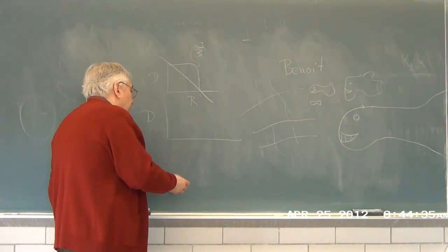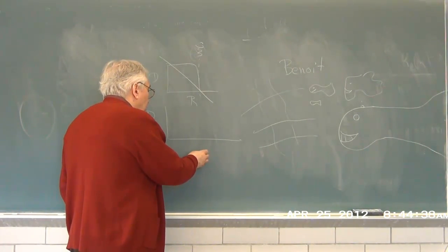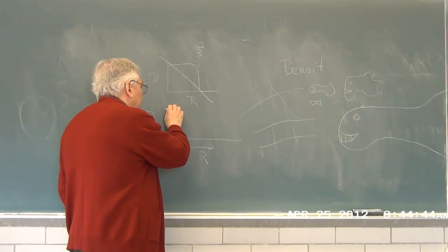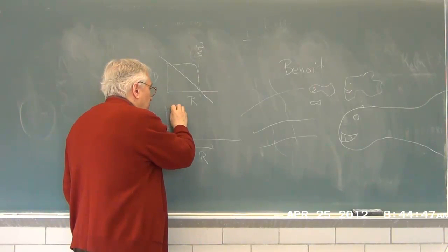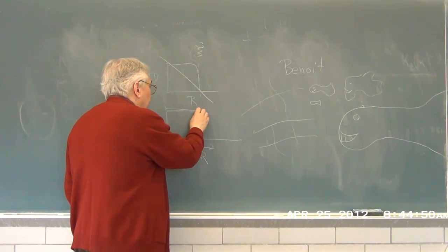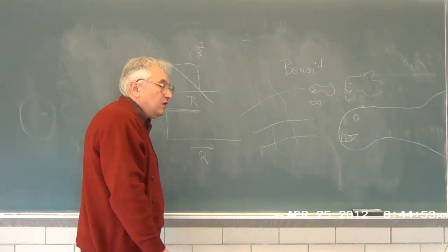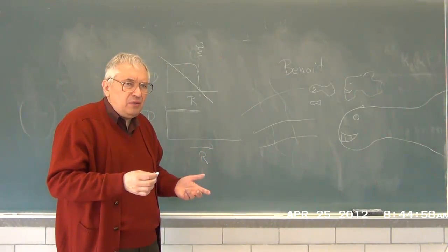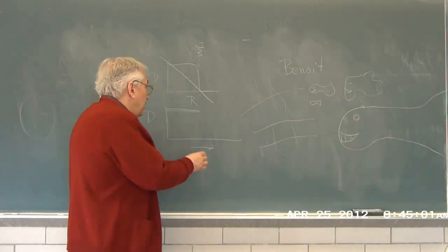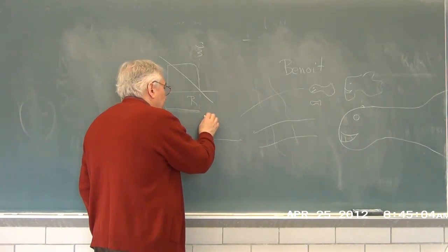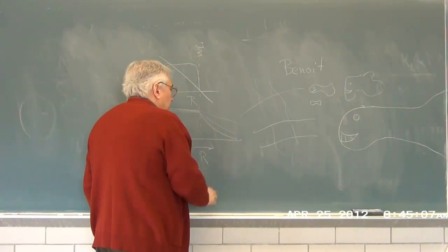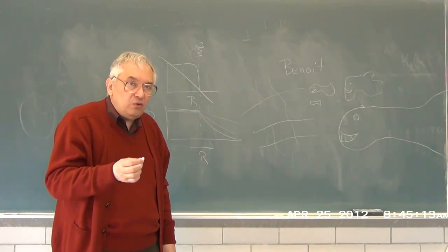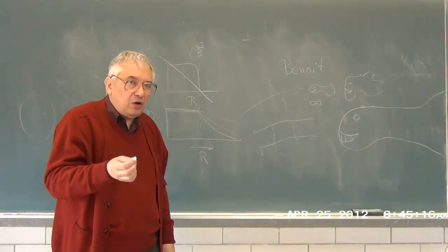And for example, you find, here's R increasing, and if you plot the relaxation rate versus probe size, you discover, for example, for one of the relaxation rates, the diffusion rate does not depend very much on polymer concentration. It does a little bit, until you get up to a critical size, and above that size, there's a much more dramatic dependence of the diffusion rate, or rather that mode, relaxation rate, on particle size.